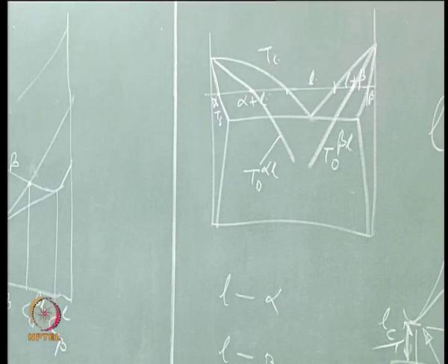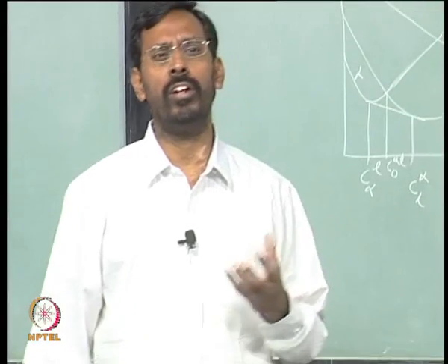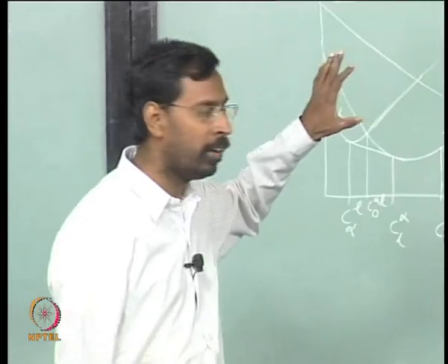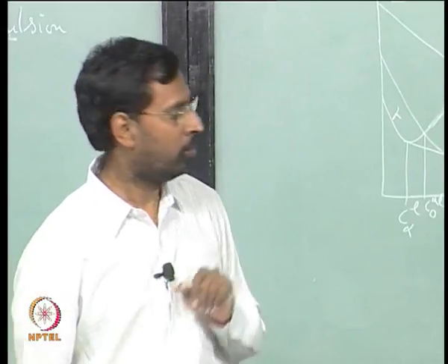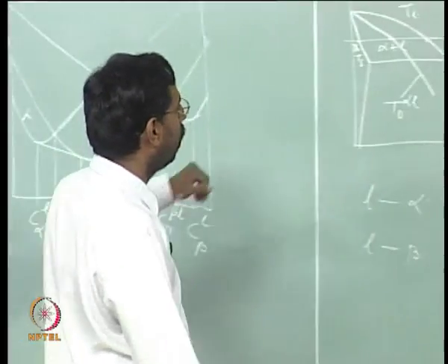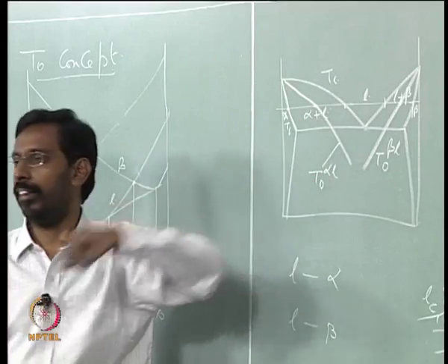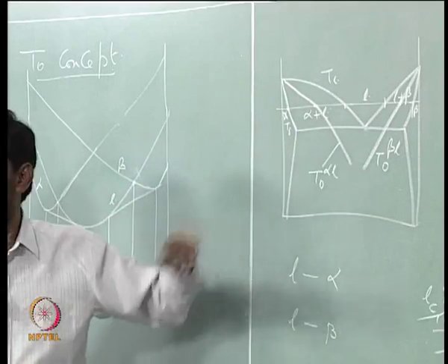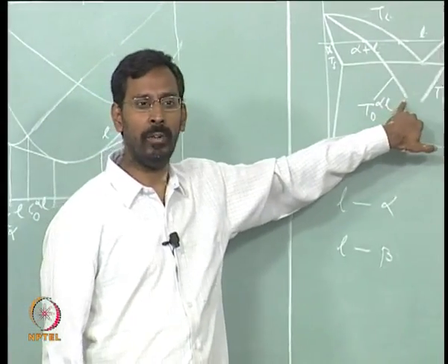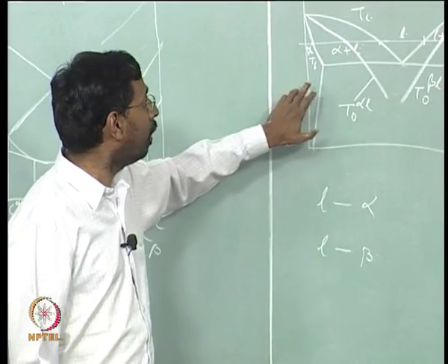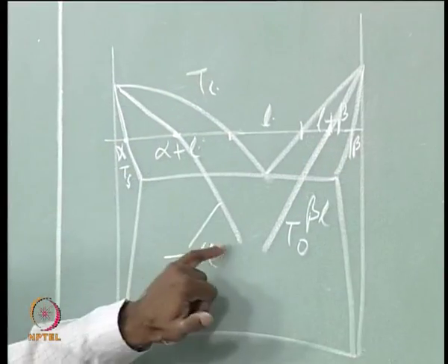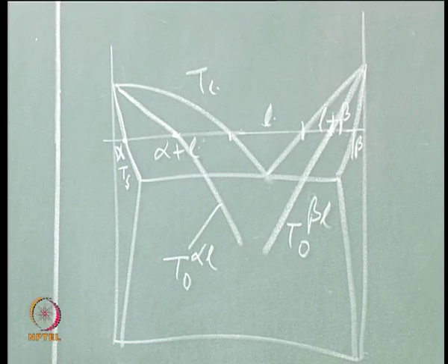These two are very important concepts when you are talking about non-equilibrium solidification. The whole microstructure development in non-equilibrium solidification just depends on this concept. So, please try to understand this. Now, this T naught is a calculated value based on the free energy concept, whereas for the whole phase diagram other than these 2 T naught curves, you do not need free energy calculations to get that.